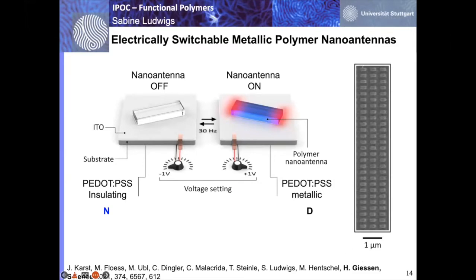expert who managed to structure this PEDOT:PSS in little nano antennas, sub-wavelength nano antennas, and then putting the whole thing also in an electrochemical setup and going with an IR laser and then looking at the transmitted intensity, we can produce nano antennas, which we can switch off when the PEDOT:PSS is insulating and switch on when the PEDOT:PSS is metallic. And this metal-insulator reversible switching of the material properties of the plasmonic resonances essentially works at very high frequencies, here at 30 Hertz. And this is because these are really small feature sizes. So look at the length scale here.